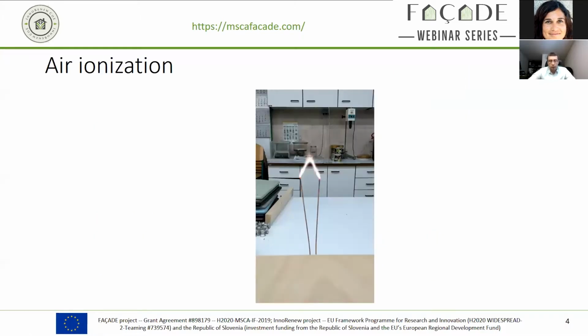Speaking of this ionization of the air, that is provided by electrical energy, and the easiest way is to provide high enough voltages that the breakthrough happens, that the air starts to ionize. Now, we all know how this looks if we just take the high voltage on two contacts and increase the voltage to a high enough level. What's happening is we're getting an arc, and so this is not really cold. A hot discharge is not really in a state where we can use it suitably for any bio-based material, because it will just start to incinerate the material.